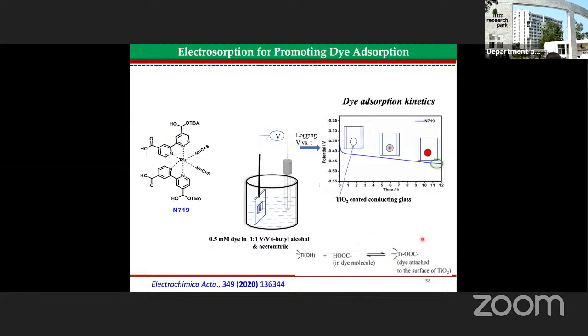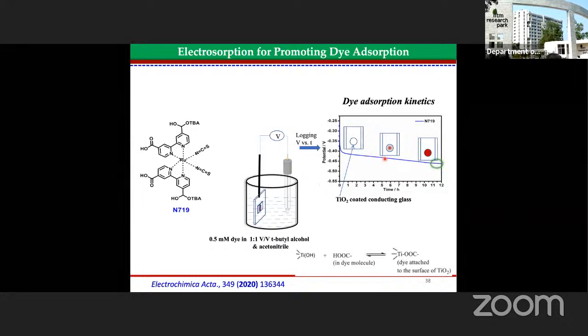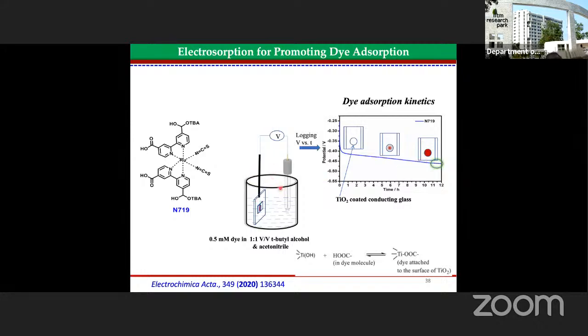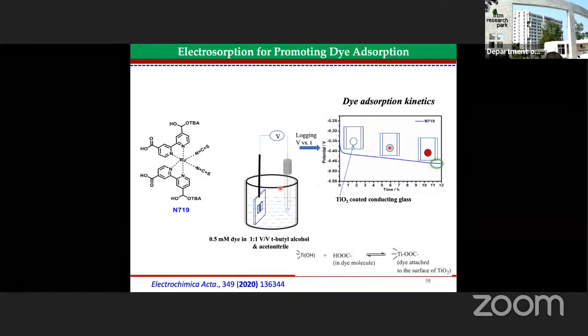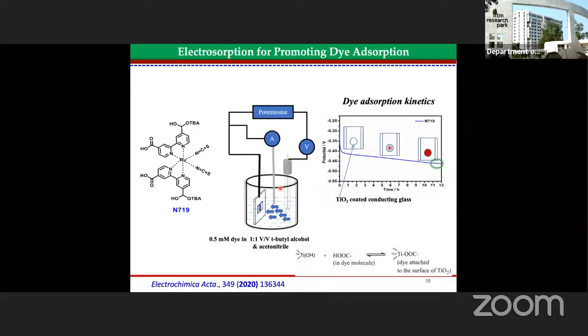We could see within 1 hour we are able to fully dye the surface. This conventional method typically takes about 12 hours to completely dye the TiO2 surface, whereas by this potential application method, within 1 hour we can coat the entire dye on the TiO2 surface. That's the idea here. So this is how this process happens when you apply potential.